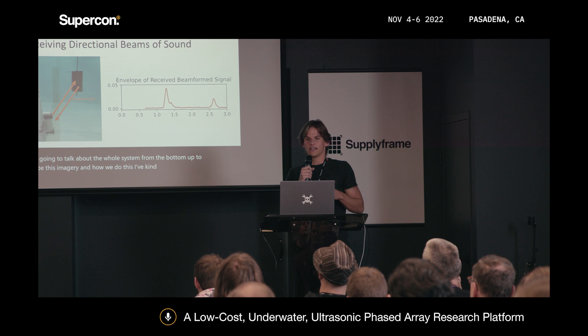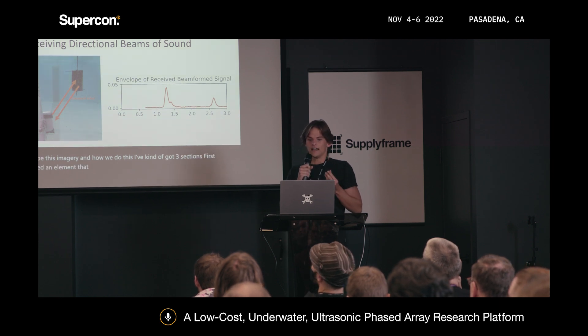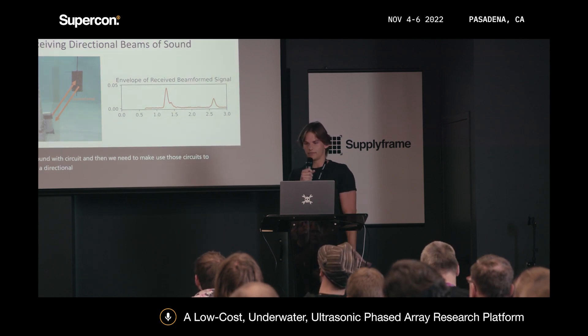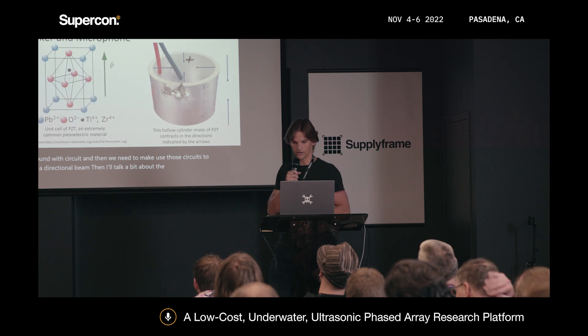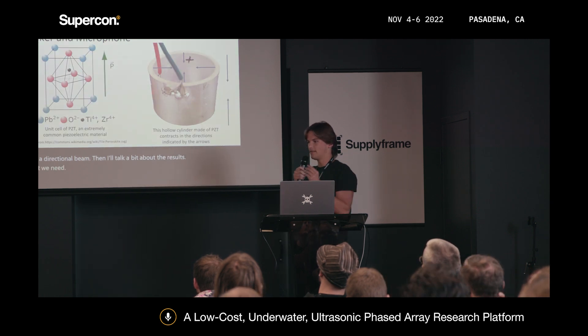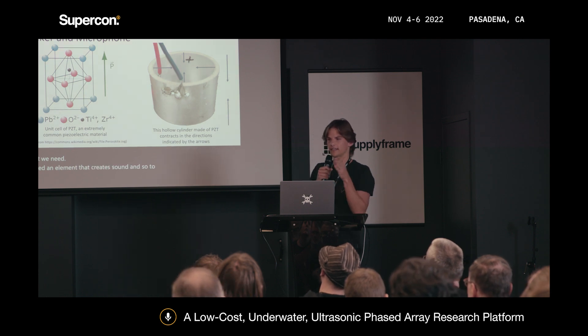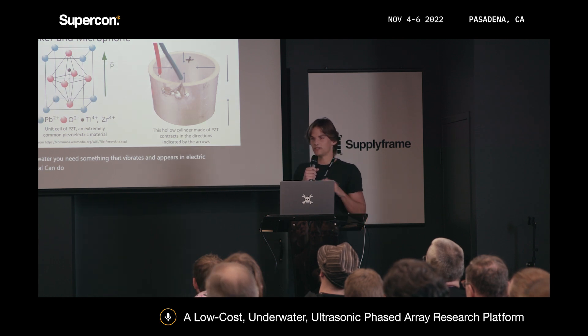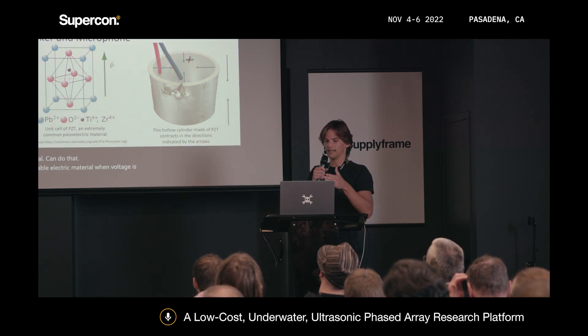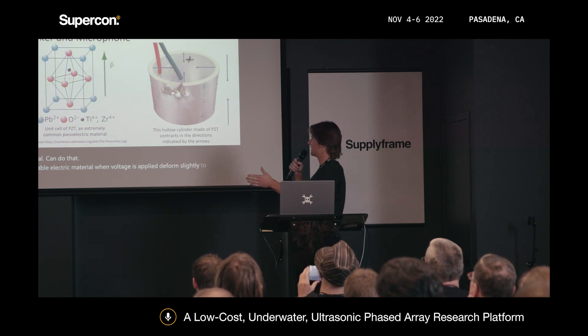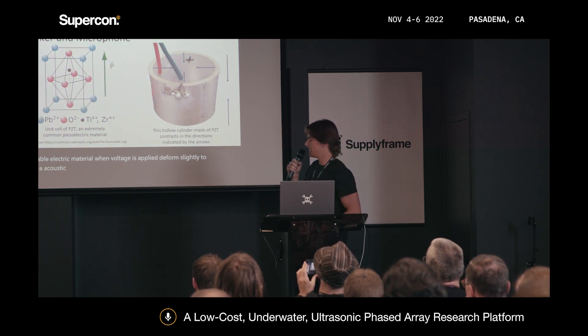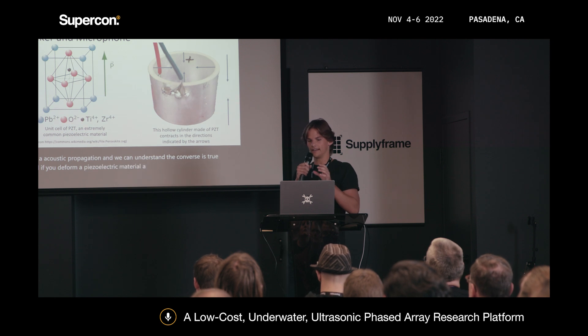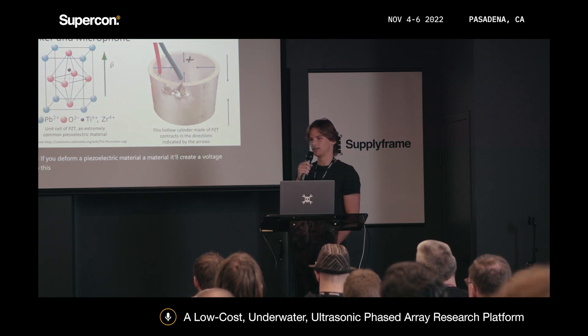To create sound underwater, you need something that vibrates, and a piezoelectric material can do that. When voltage is applied, a piezoelectric material deforms slightly to create acoustic propagation. The converse is also true: if you deform a piezoelectric material, it creates a voltage. So this piezoelectric material can act as a transducer — both a speaker and a microphone. We can intuitively understand this by looking at the unit cell of PZT, an extremely common piezoelectric material. In this unit cell there is a positively charged atom that is slightly off-center, creating a charge distribution with a positive charge at the top and negative at the bottom.